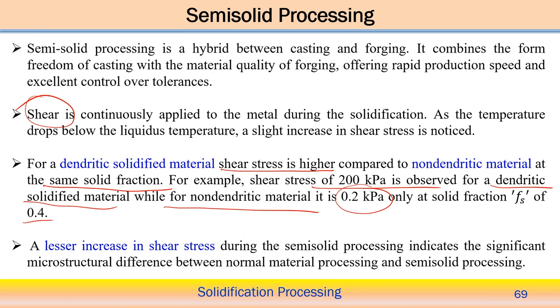Based on that, shear stress is different in these two cases, even for the same amount of solid fraction. When you try to produce some kind of semi-solid in this case, the low increment of the shear stress during semi-solid processing indicates that there is a significant microstructural difference between normal material processing and semi-solid processing.